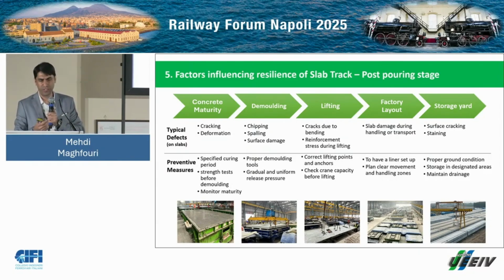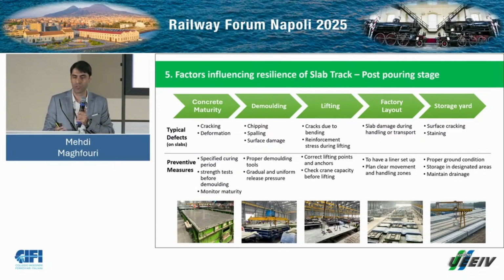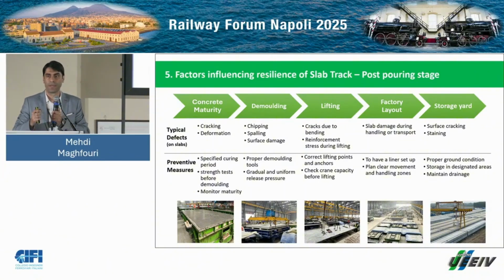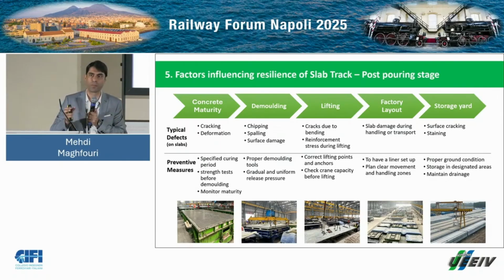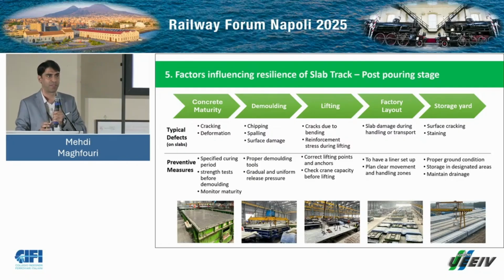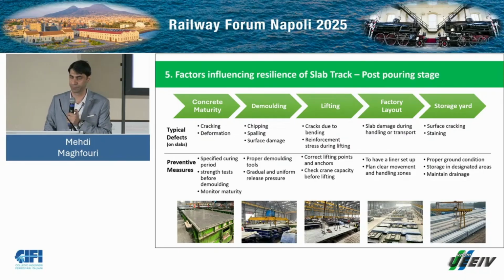And here I also mentioned that, for example, proper demolding tools we have to apply, with gradual and uniform release pressure. You know, if we don't use the proper demolding equipment, sure, we will have a lot of issues with defects on the slabs. We have faced this problem. We have faced this issue. That's why a proper frame shall be designed and implemented for the demolding.